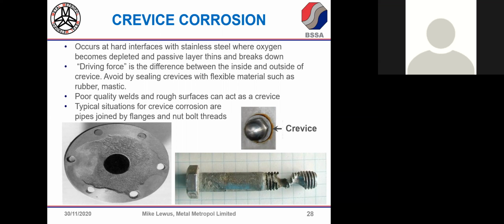You'll see the other two examples, a huge area corroded away under a flange, and a huge part of the load-bearing cross-section of a bolt. You wouldn't see the damage, on the flange or the bolt, until something critical happened, either the pipe leaking some noxious liquid or the bolt's supporting structure collapsing. So in certain cases it's very wise to understand the operating conditions, whether there's a risk of these corrosion mechanisms, and choose material that will combat, or at least help you to mitigate, the risks.